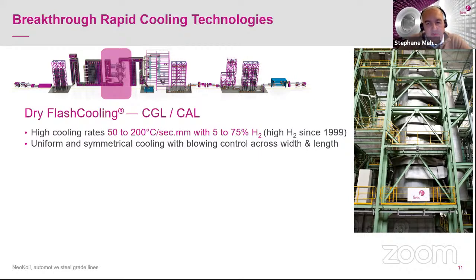Since 99, we have developed the potential of hydrogen to enhance the cooling capabilities of these sections. And we have more than 25 references operating today with flash cooling with hydrogen above 30%. Some of the latest, the 3 latest POSCO lines in Gwangyang in South Korea, are all equipped with 75% hydrogen flash cooling from Fives. So we can reach cooling rates up to 200 degrees C per second for 1 millimeter thick products, with a very uniform and symmetrical cooling of the blowing, so that we can avoid any cool buckle risk and surface defect.